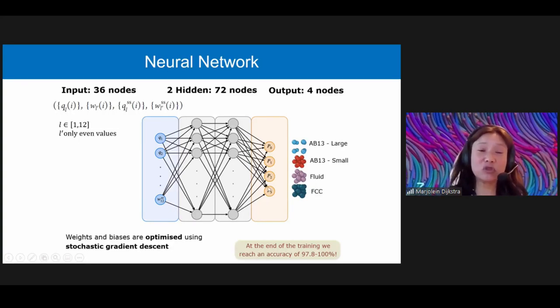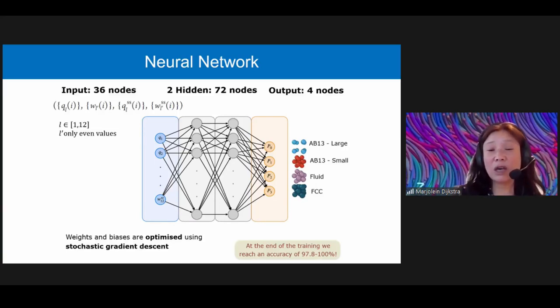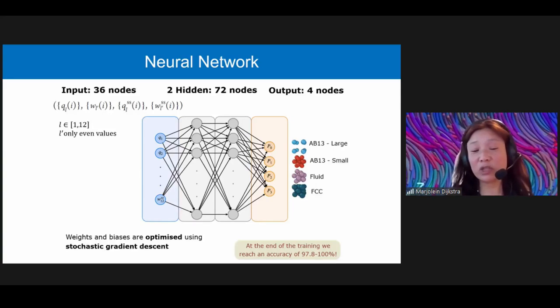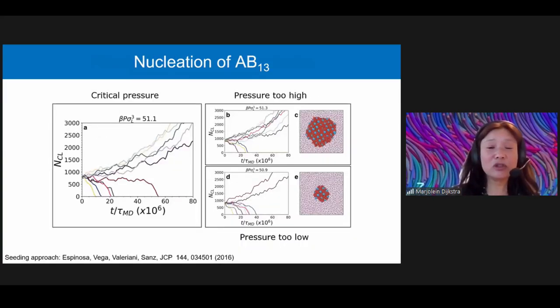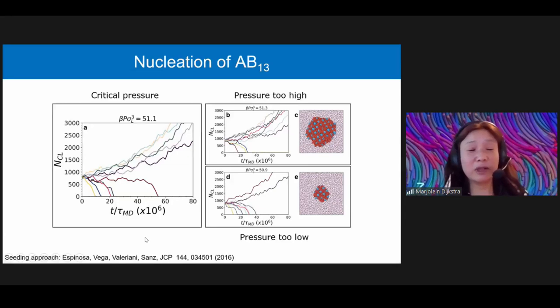And by training such a neural network with many labeled data, so we use bulk configurations of all these 3 different phases, the AB13 fluid and the FCC phase, we find that the trained neural network has an accuracy of 98 up to 100%. And so this allows us, using the seeding approach that was introduced by Eduardo Sanz and Chantal Valeriani, to study nucleation of this AB13 crystal.